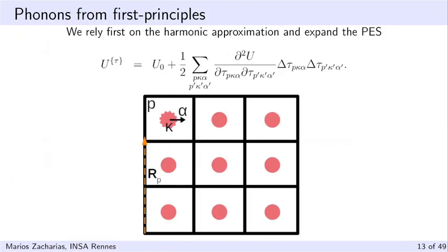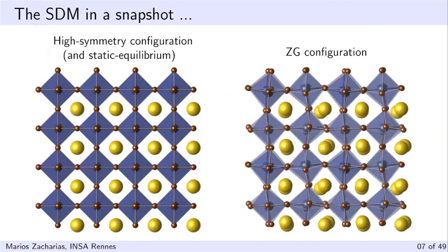If I use this structure, for example, for silicon without any thermal displacements, you'll get an absorption onset at the direct gap because we are not including any electron-phonon coupling effects, all right? But if you displace your structure along all phonon modes, you are incorporating the effect of electron-phonon coupling, and you can reveal indirect optical absorption.